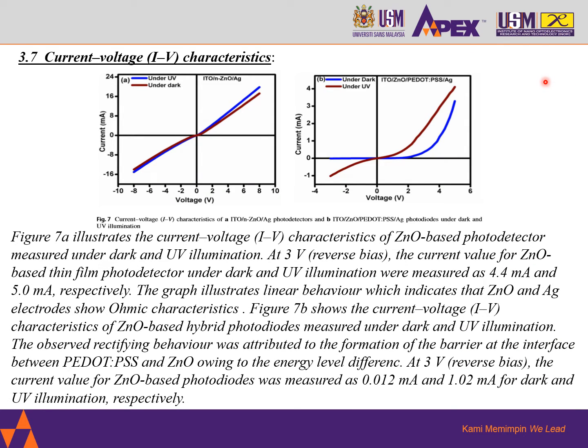Now the current-voltage (IV) characteristics. Figure 7a illustrates the current-voltage characteristics of the zinc oxide based photodetector measured under dark and ultraviolet illumination. At 3-volt reverse bias, the current value of the zinc oxide based thin film photodetector under dark and ultraviolet illumination was measured as 4.4 milliampere and 5 milliampere respectively. The graph illustrates linear behavior, which indicates that zinc oxide and silver electrodes show ohmic characteristics.